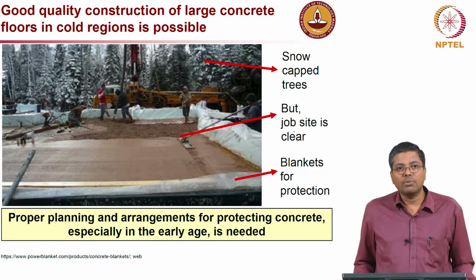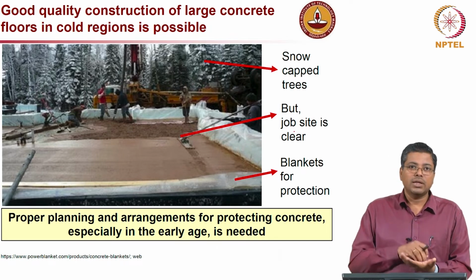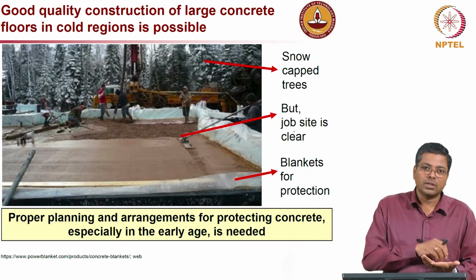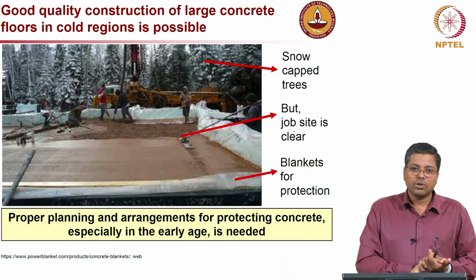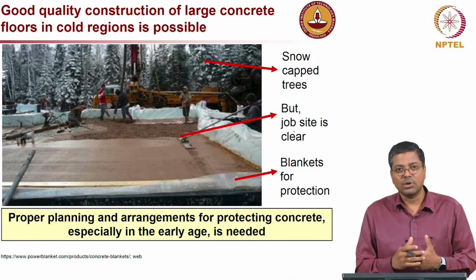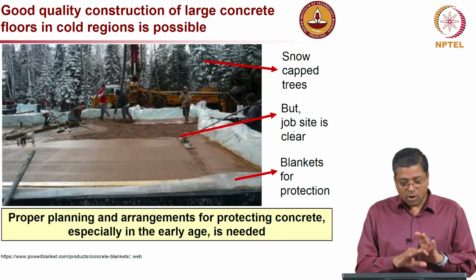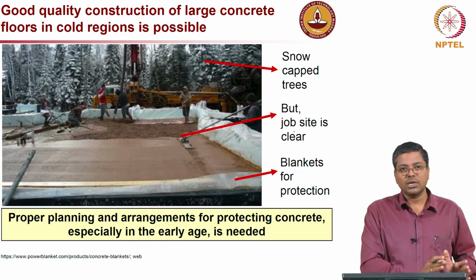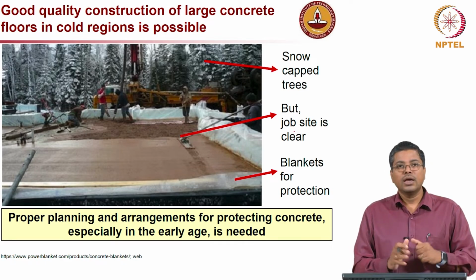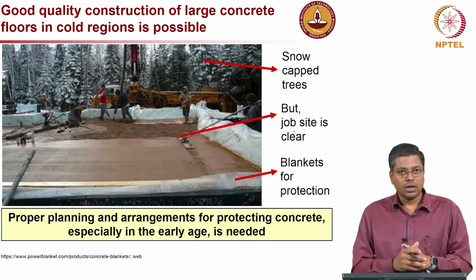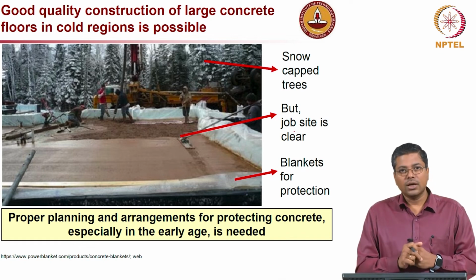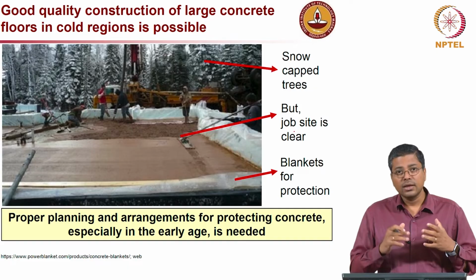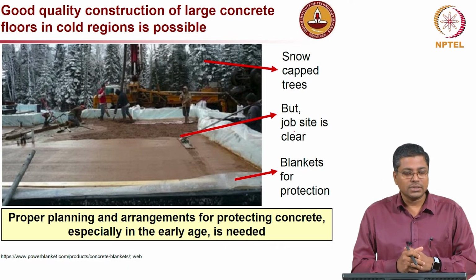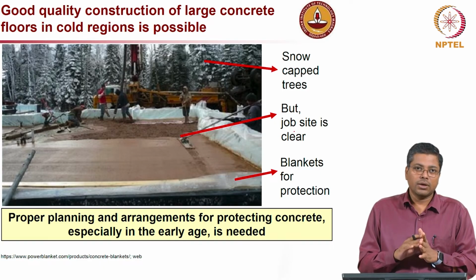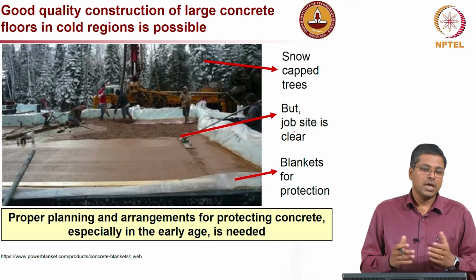So, if we do all this with proper planning and arrangement for protecting, the protecting of concrete is also very important. It is not only the materials which you put, like the finely ground cement or a cement with high C3S or C3A, and chemical admixtures like antifreezing chemicals or accelerating admixtures. All that is fine when you talk about the material aspect. Then you have to place the concrete properly and make sure that in the initial stage you have sufficient moisture available as water, preventing frost attack, and then make sure that the 3.5 MPa strength is gained, and then protect the concrete by preventing further moisture loss, and also heat loss.